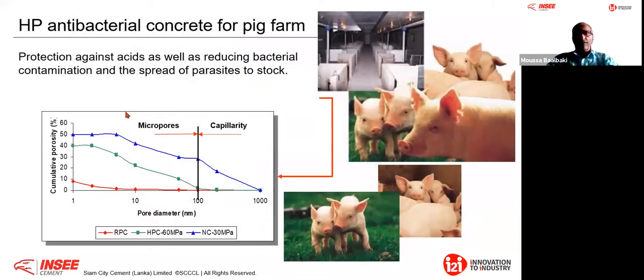Okay, therefore, this is, for example, a personal experience I have from Canada. When I was in Canada, we developed there, at the legacy of Holcim, what we call the high performance antibacterial concrete for pig farms. The problem here is that with these small pigs, the parasites that sit in the stable, with time they contaminate the small pork. Suddenly they get sick, and the death rate can go up to 25%. And in terms of productivity, this is the big loss. Second, there is some market in Japan, for example, they are ready to pay more than a 15% premium if the small animal is not treated with antibiotics. This is why we call this a high performance antibacterial.